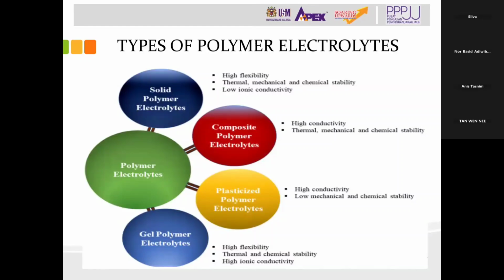This metal-polymer interaction can be affected by factors such as the nature and distance between the functional groups of the polymer, molecular weight, and nature of branching. When the polymer electrolyte is placed in an electric field, the ions start to move from one coordination site to another, and it occurs due to weaker interaction between the metal ion and the functional group of the polymer chain. For solid polymer electrolytes, we have high flexibility, thermomechanical and chemical stability, and also low ionic conductivity.